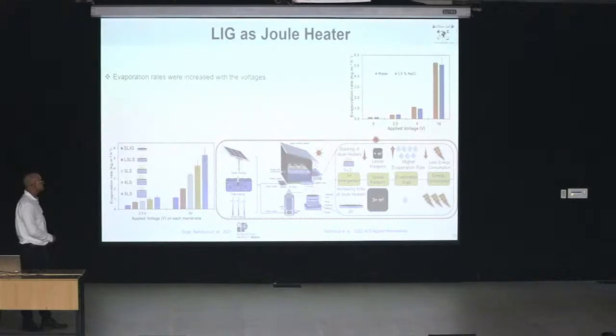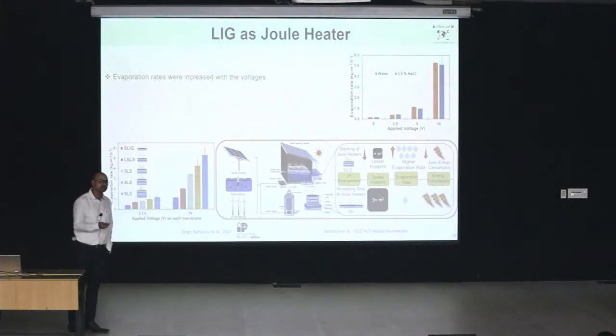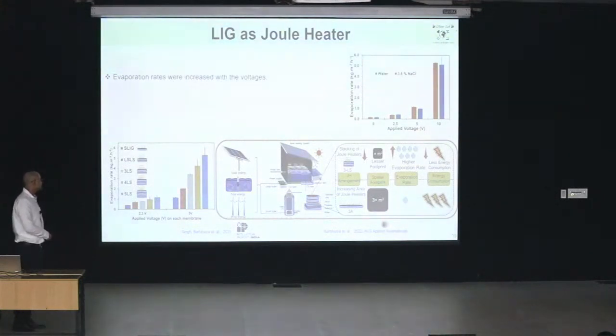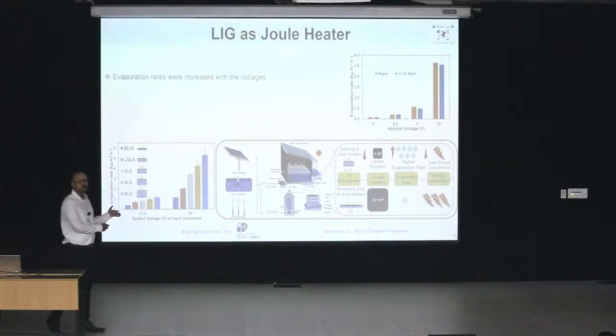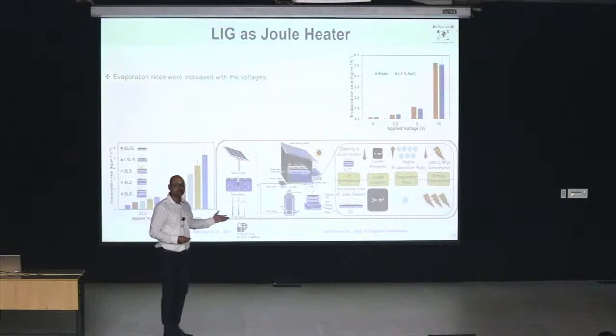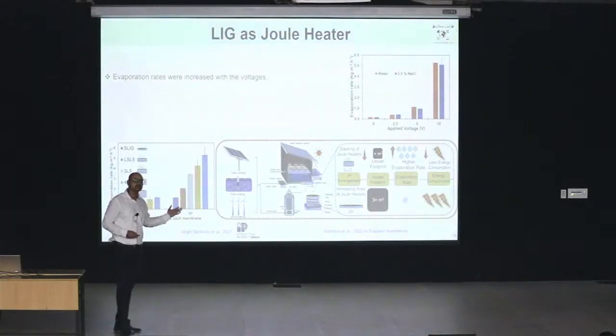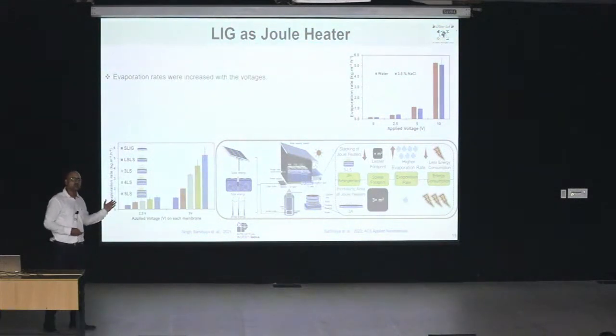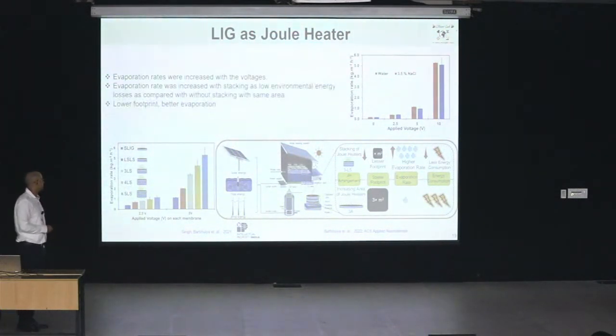And what we have demonstrated is that just by stacking these surfaces, we can gain multiple things. For example, we can reduce the footprint. We can get almost 7 times higher water evaporation with just 3 layers of stacking, and energy consumption was 3 times less compared to the single stage. This work was recently published in ACS Applied Nano Materials, and we have also filed an Indian patent on this. So it has shown how these laser induced graphene filters, normal filters, I am not talking about membranes till now, just these filters which were fabricated in a single step, which are low cost, can be used very effectively for desalination.